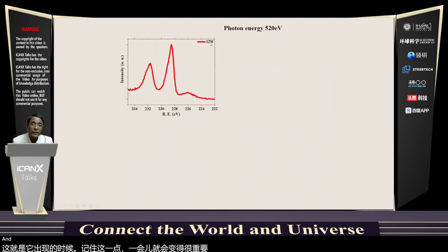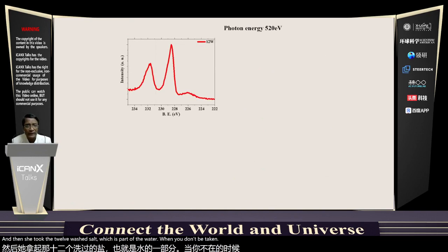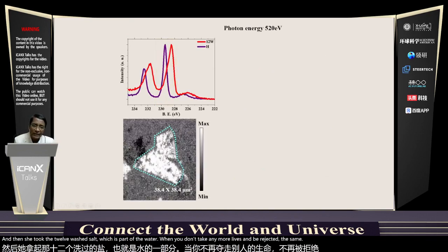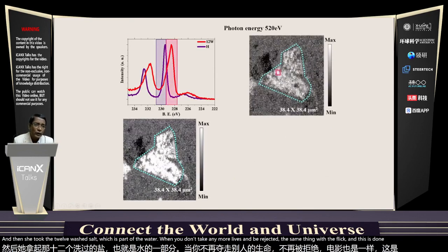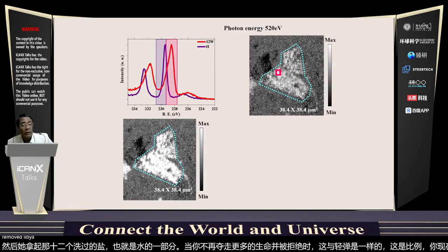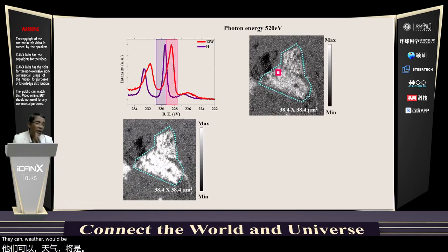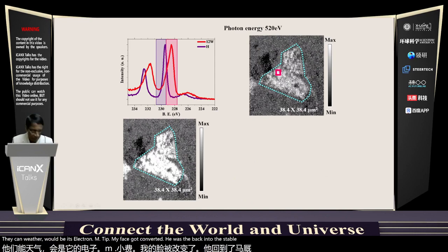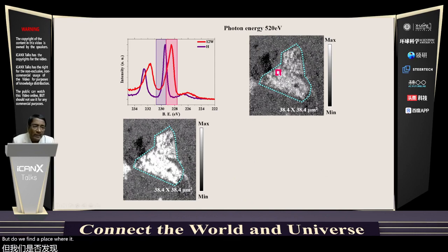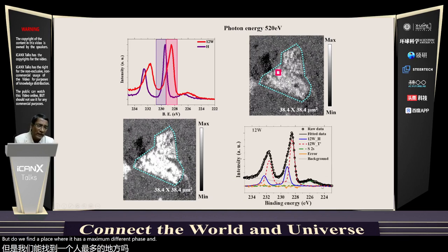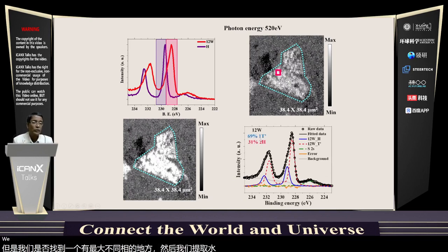And then she took the 12 wash sample, which is thoroughly washed, where you don't detect any more lithium, and did exactly the same thing. This is the flake and this is the ratio. You can now see that the T prime phase has become much weaker all over the place, simply because I have removed lithium. Lithium went away with its electron and the T prime phase got converted hugely back into the stable H phase. But we find the place where it has the maximum T prime phase and we extract it, and we find it's about 70% T prime phase and 30% H phase.